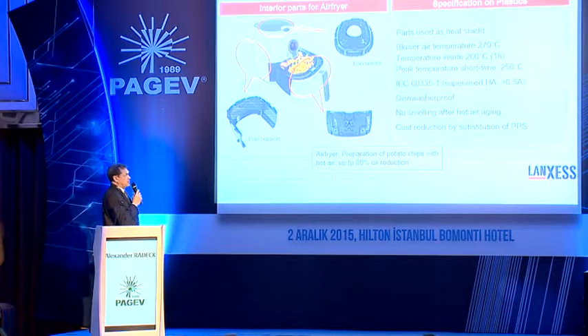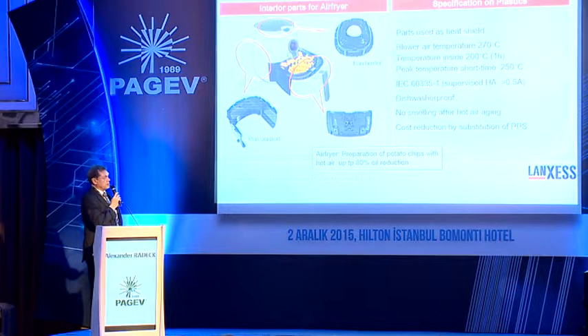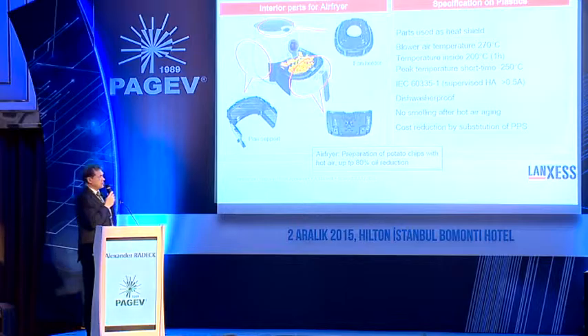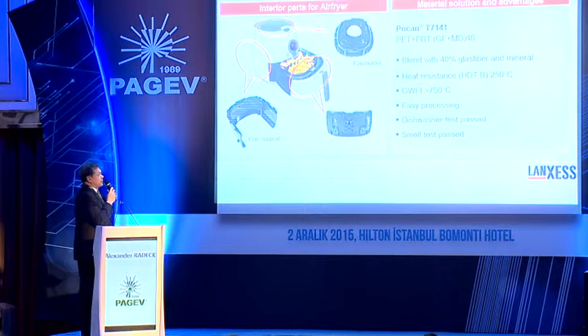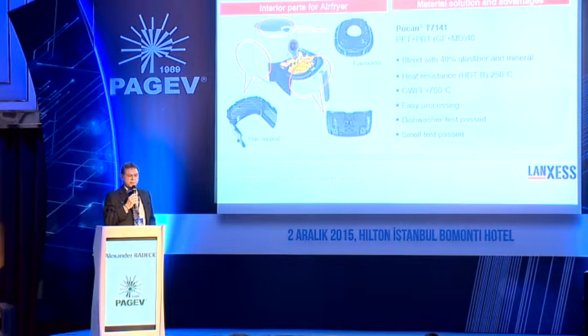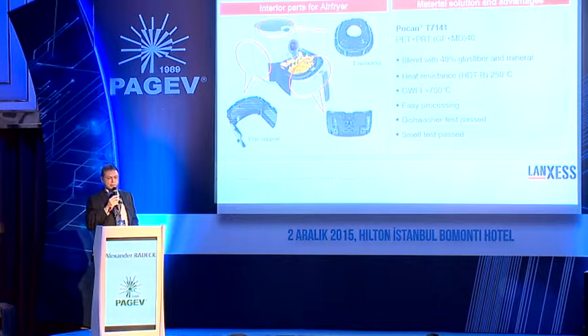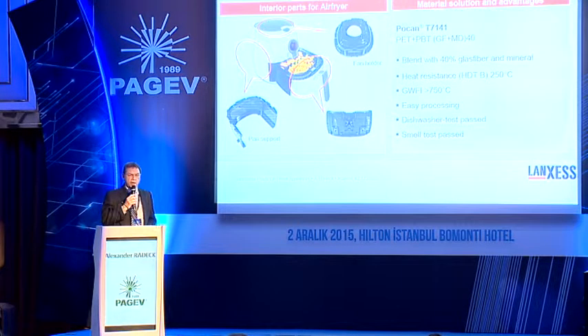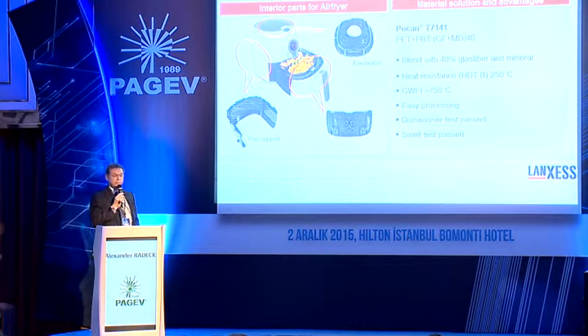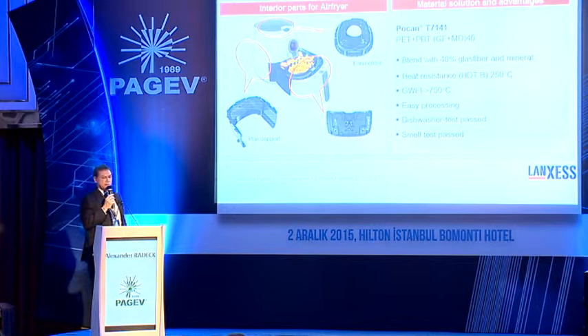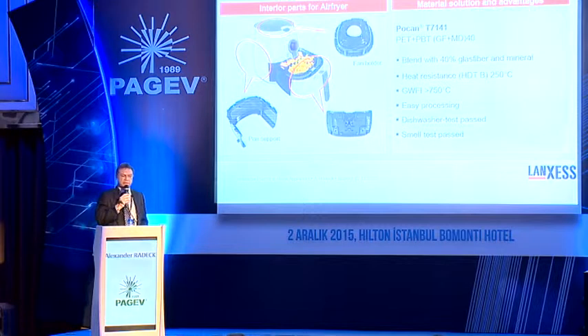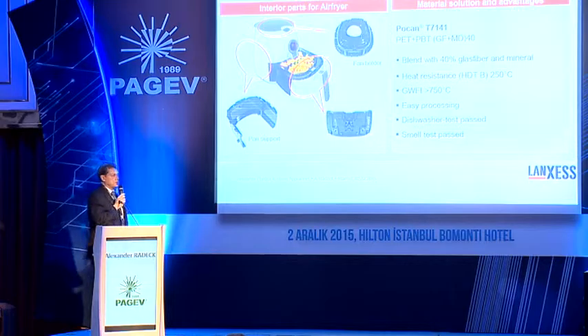There were also additional tests with regard to dishwasher proofness. There was no smell allowed after heat aging. And of course there should also be a cost advantage compared to the former solutions which used PPS. As I said, a PET PBT blend was chosen for this, reinforced with glass fiber and mineral, 40% filler content. With the PET, we have an increase in the heat resistance. The HDT, the heat deflection temperature, of 250 degrees was sufficient here. The glow wire flammability index is 750 degrees Celsius, which is also fulfilling the standard. With the PET, we also have an improvement in the easy flow, which enables an easier molding process. The dishwasher test was passed, as well as the smell test.